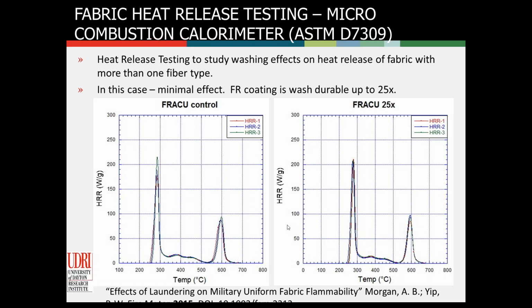In the cone calorimeter, we're not seeing any differences in heat release, but what about when we take the fabrics and we wash them? Do we see any difference in the microcombustion calorimeter? And the answer is yes, we do. There's some minor tweaks as a function of the washing. There's some minor reductions in peak, which is some of the initial flame retardant washing off, and then after that, there's no change. So after the first wash, which is data I'm not showing here, you see a slight reduction, and then it stabilizes. So the stuff on the surface of the fabric washes off, but then what's embedded in the fibers is still intact.